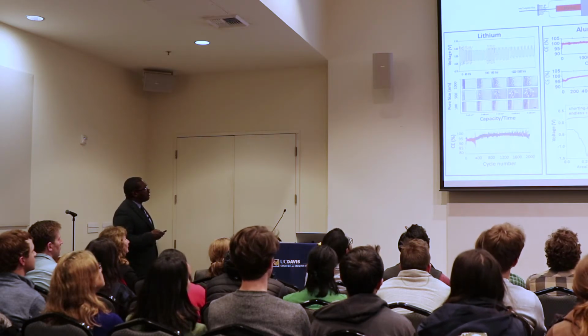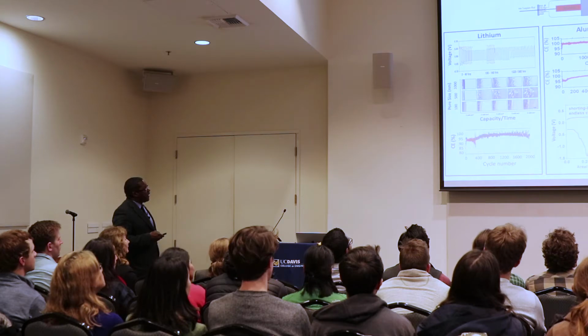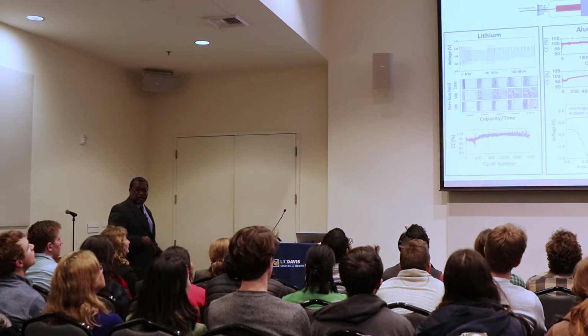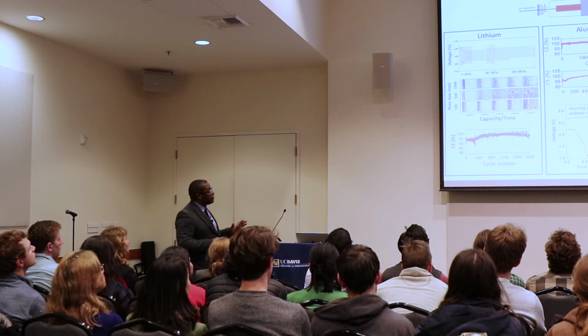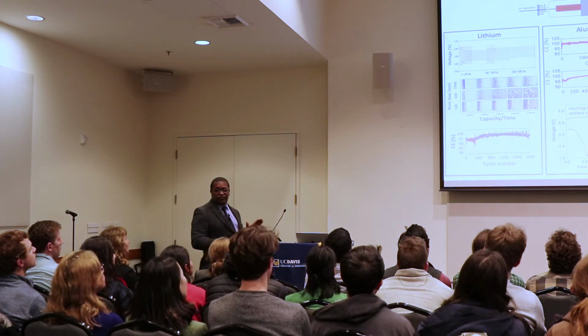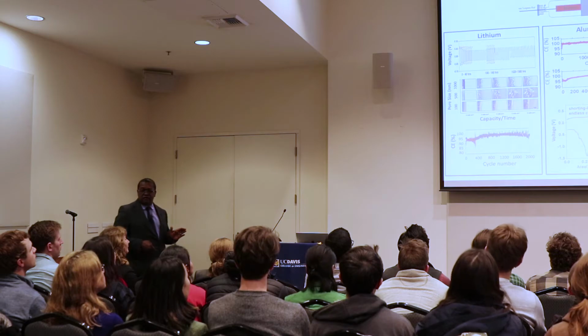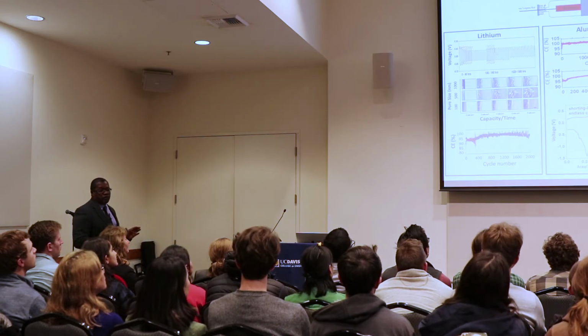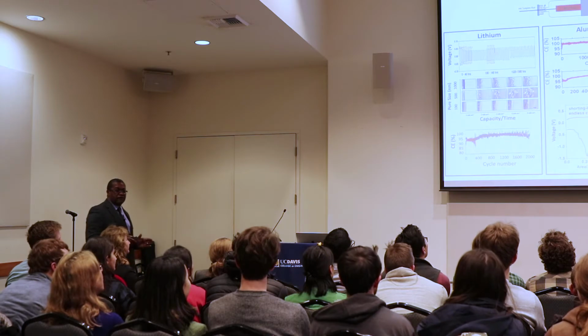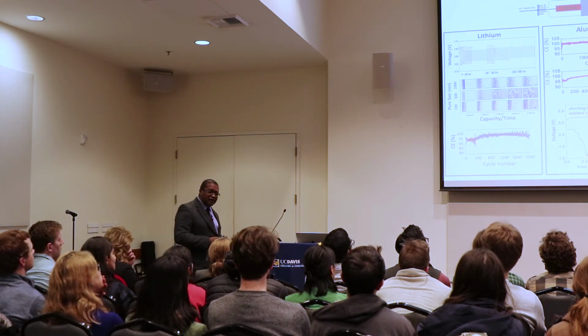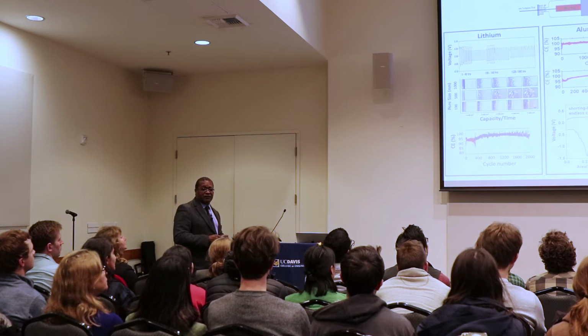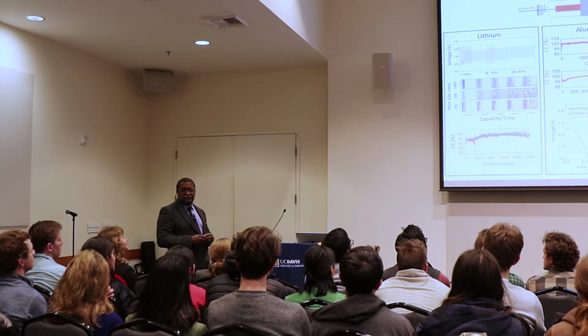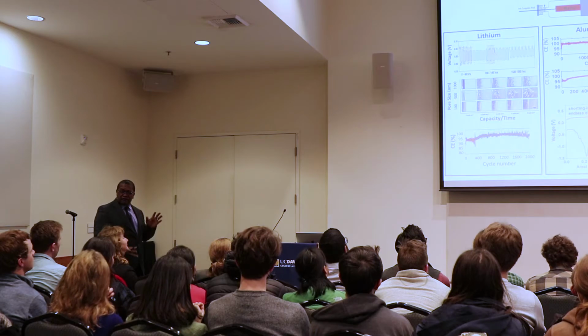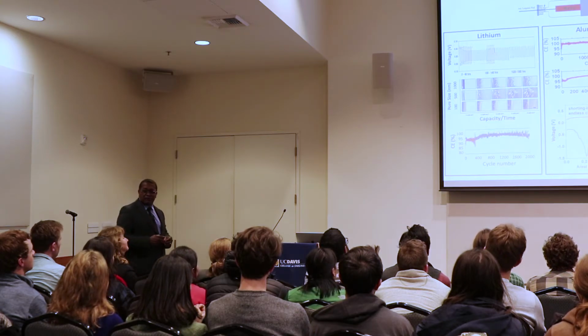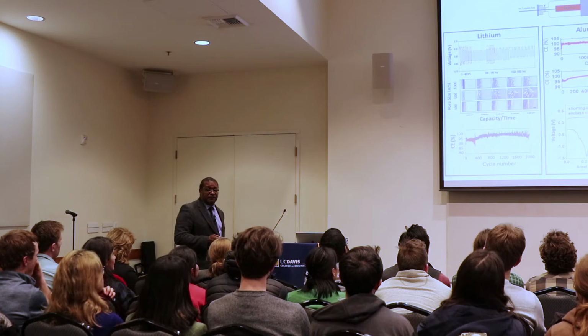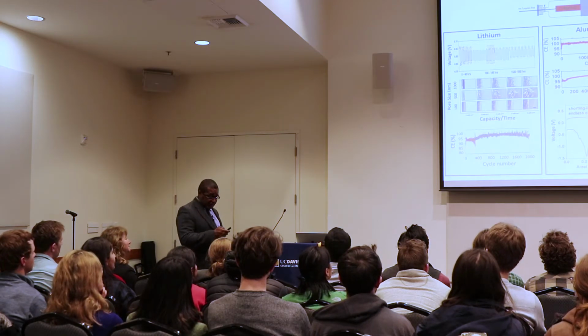So we did lithium, we did aluminum, we did zinc. With lithium, we're up to 2,000 cycles with no evidence of dendrites. For aluminum, we're up to 30,000 charge-discharge cycles with no evidence of dendrites. For zinc, we're up to 10,000 cycles with no evidence of dendritic shorts, indicating that this is not a technique that's just limited to lithium because it's physical. It seems to be applicable to any metal. It's as potent to some extent in solving the problem, and we think this is because it relies on physical forces to solve that problem.